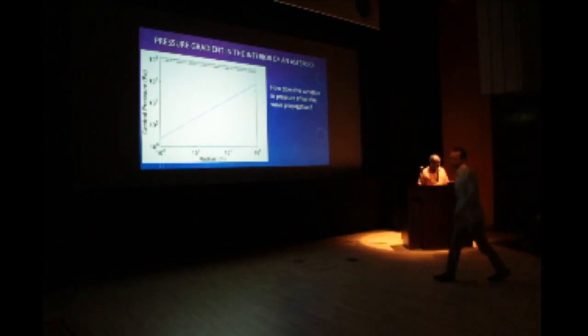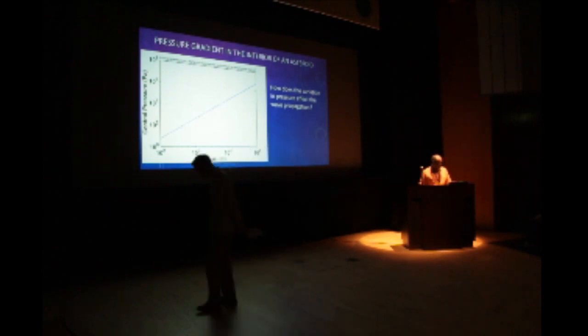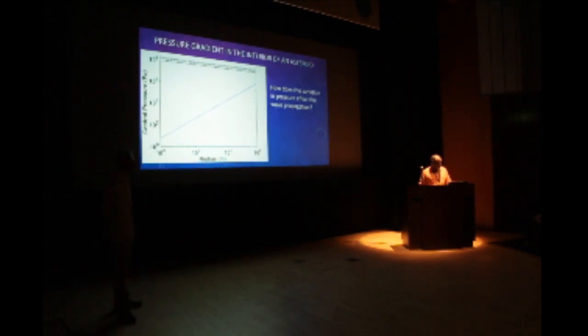Yes, I find it gratifying to see in your simulations and also in the previous talk that size distributions of the particles making up the target body are included instead of the same size. On the other hand, I think you should extrapolate that to what is a pretty common condition, which is a marginally catastrophic breakup and reaccumulation in which the largest part of the rubble pile is a substantial fraction, 20, 30, 40% of the mass of the original target, and have the size distribution go down from there.